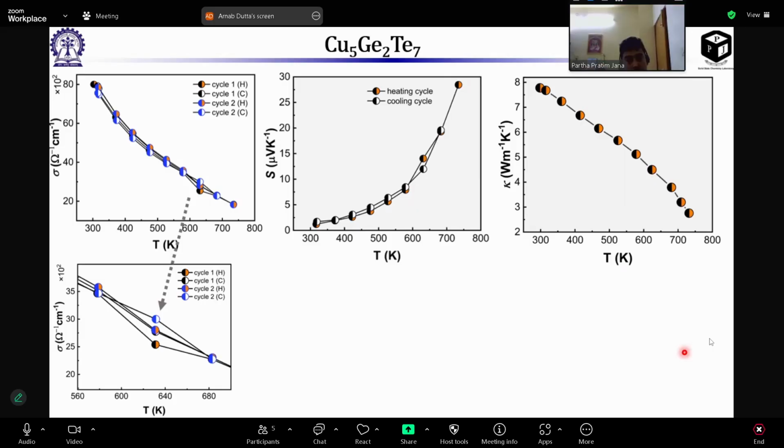You see, the conductivity is measured, the temperature is observed. The only variable left is the Lorentz number. So if your L sigma T is somehow giving you values that are too high compared to what is observed, then something weird is going on, right? That value must actually be smaller than we expect. That means the Lorentz number must be smaller than we expect, and it could be coming from this dimer effect or something. And that's fascinating.